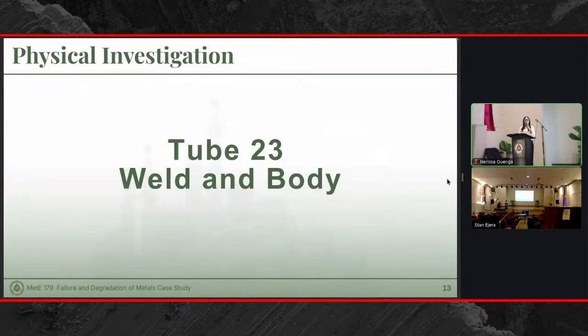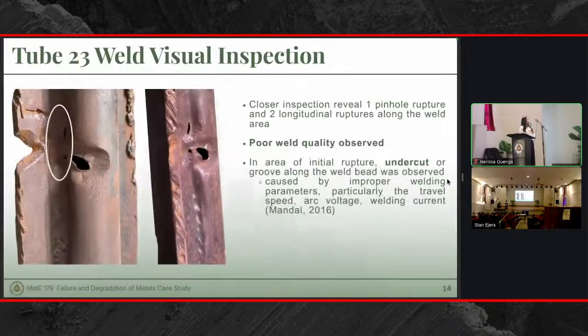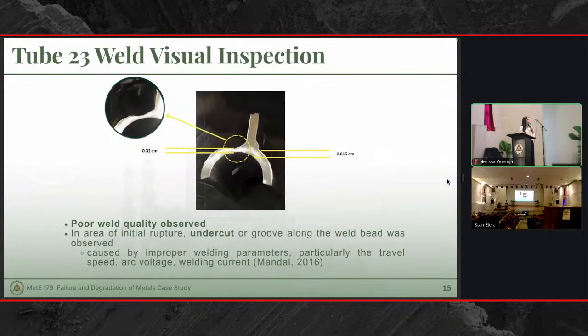Moving on, we conducted investigation on tube 23, on its weld and body. From visual inspection, we can see that there is poor weld quality for tube 23, and in the area of the initial rupture, there is an undercut or groove along the weld bead, and this may be caused by improper welding parameters. Moreover, tube 23 also experienced significant wall thinning, wherein its wall was reduced by half.